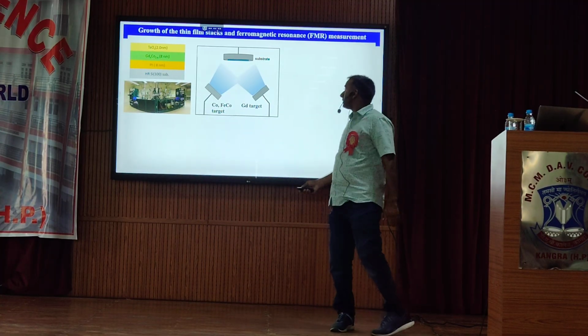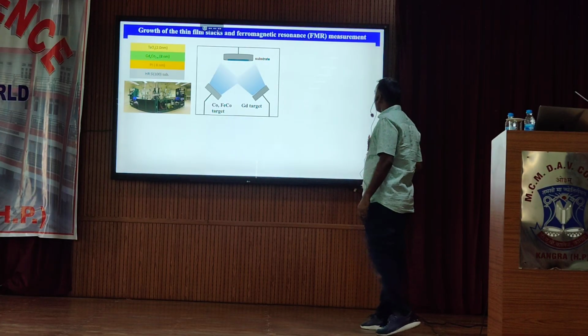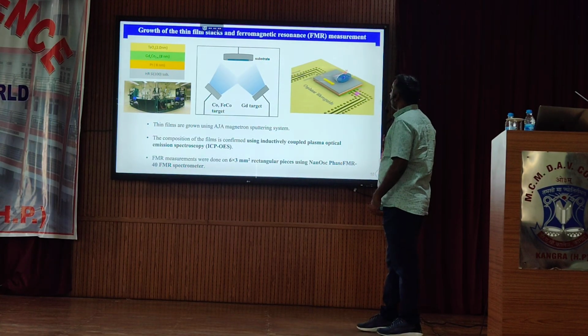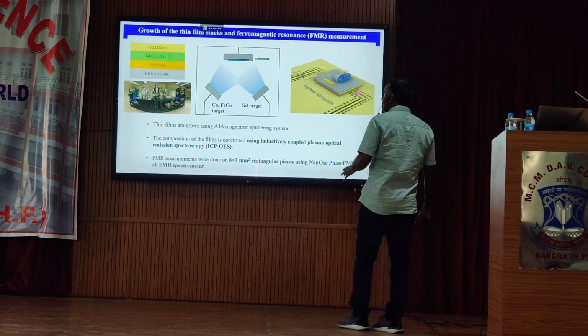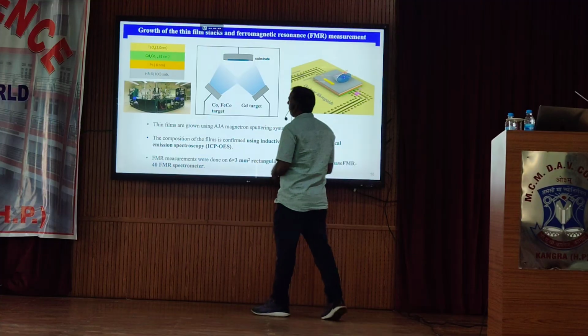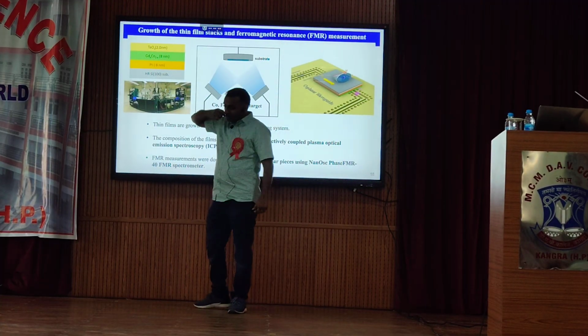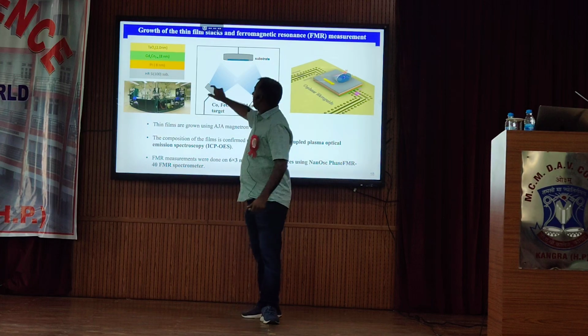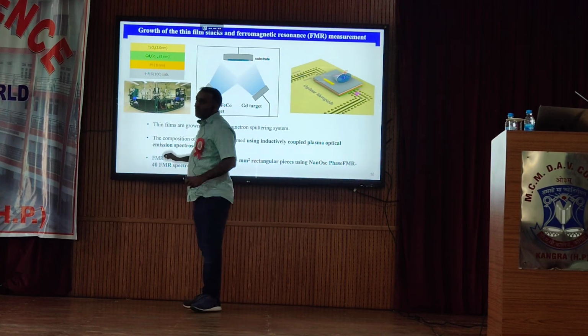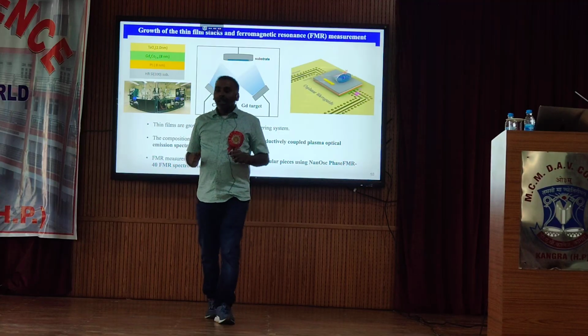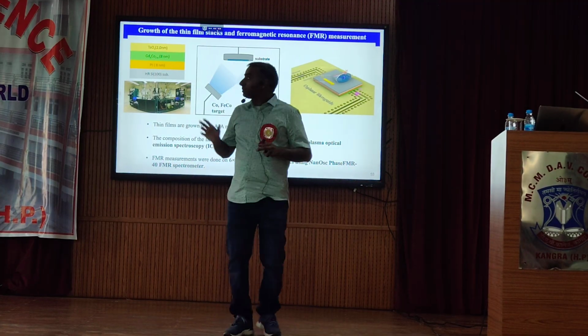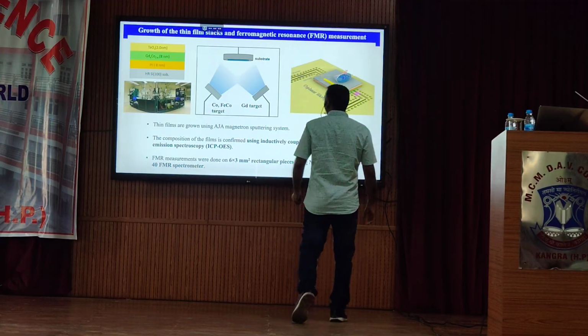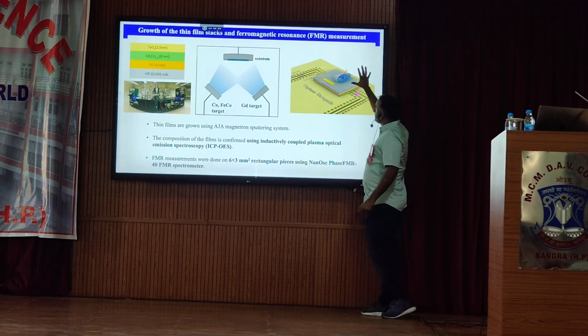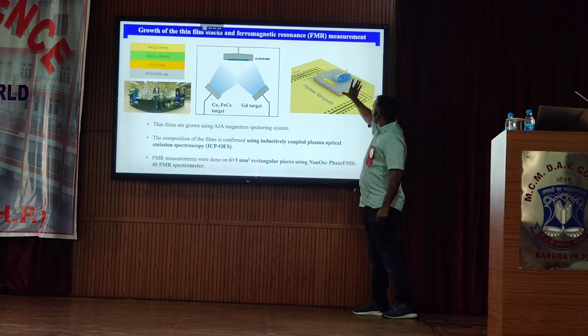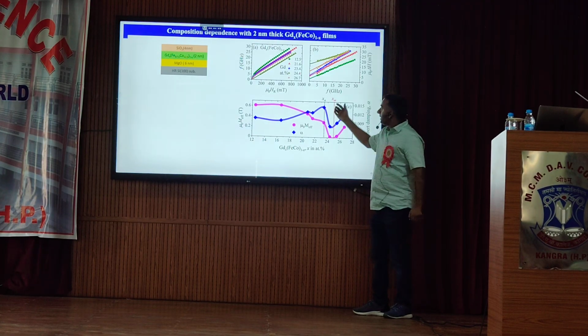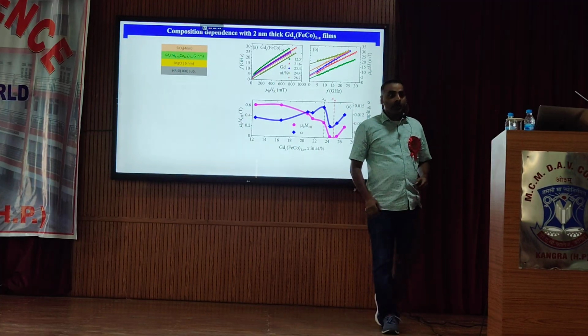We initially chose a thin film thickness of 8 nanometers. We grew these 8 nanometer thin films on high resistance silicon substrate. I have not introduced why we are using high resistance silicon, but let me touch upon it briefly. We are using silicon because we want to make our devices compatible with existing CMOS technology. After making these thin films, we use our setup for ferromagnetic resonance. We place our thin films over it and then measure the dynamics. The results of the magnetization dynamics can be seen here.